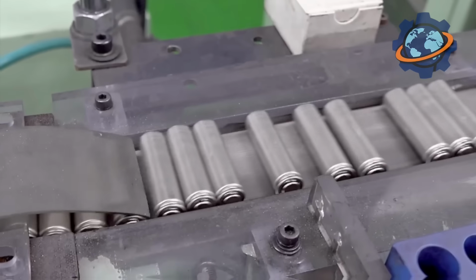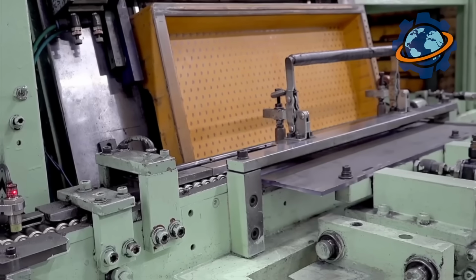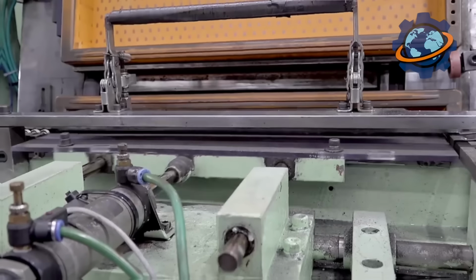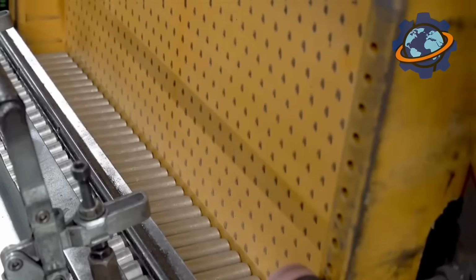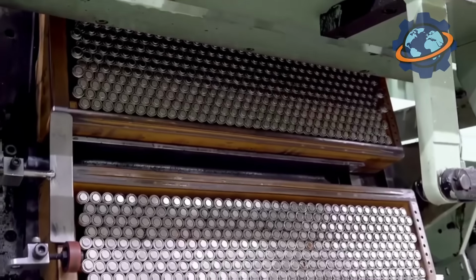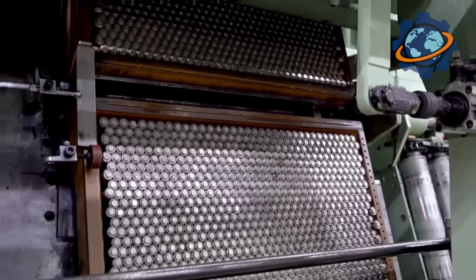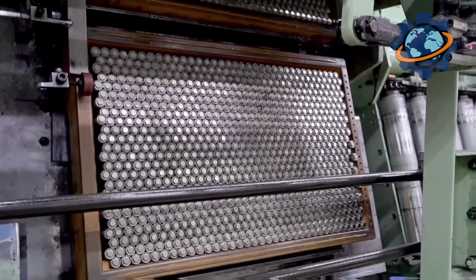The second test is weight. Too light means not enough zinc gel or paste was added. Too heavy, there might be a problem with the seal. A robot lifts it, weighs it, and compares it to a standard. A deviation of more than 5/100ths of a gram, and the battery is kicked off the conveyor, on the fly.